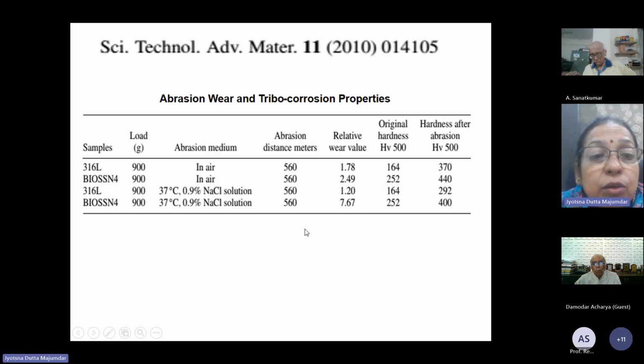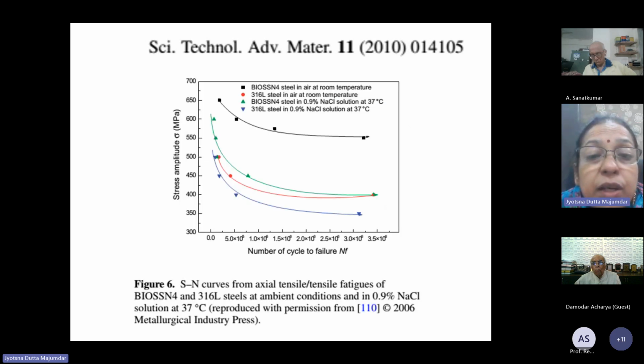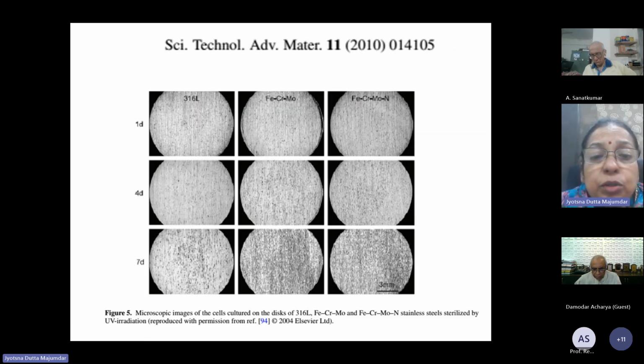Someone can always take the nitrogen containing steel and see the effect of this nitrogen on the tribocorrosion property in a more extensive fashion. If you talk about the SN curve for the nitrogen containing steel like bio SSN4, you will find that fatigue property is also significantly higher in nitrogen containing steel than in steel without nitrogen content. So it improves fatigue corrosion resistance to a large extent, it increases the corrosion resistance to a large extent, but why the tribocorrosion property is showing poor value, someone can repeat the result and check what the reason behind it is.